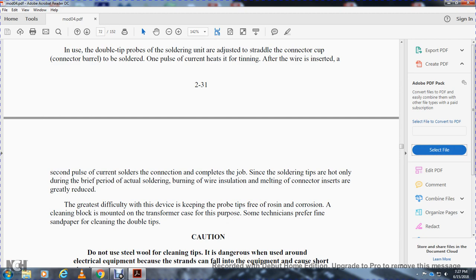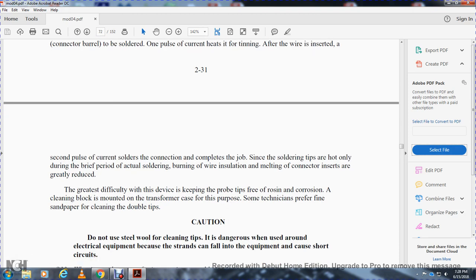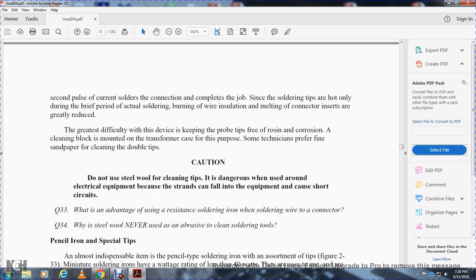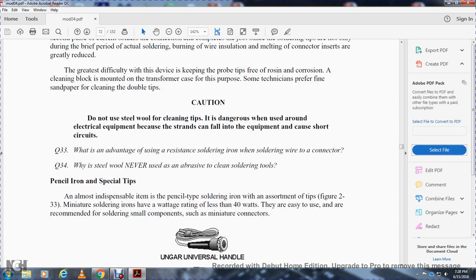The great difficulty with the device is keeping the probe tips free of rosin and corrosion. A cleaning block is mounted on the transformer case. For this purpose, some technicians prefer fine sandpaper for cleaning the double tips. Caution: do not use steel wool for cleaning tips. It's dangerous when used around electrical equipment because the strands can fall into the equipment and cause short circuits.